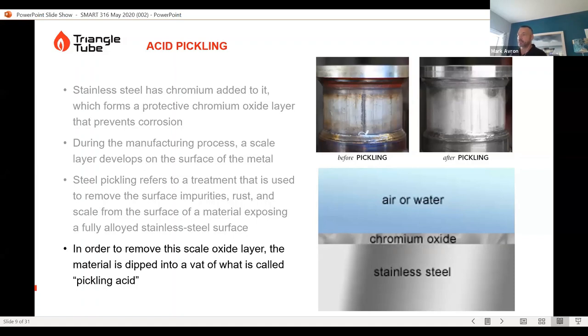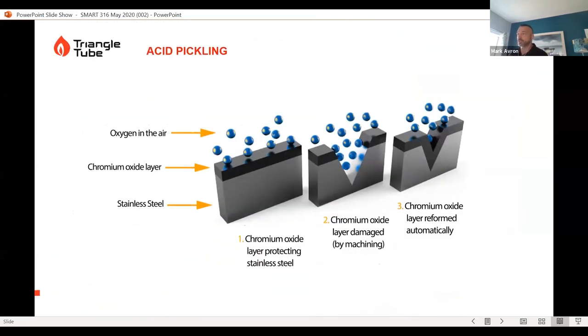In order to remove the scale oxide layer, the material is dipped into a vat of what is called pickling acid, using different acids. The difference between passivation and pickling is that passivation uses milder acids to clean the surfaces, and they don't result in as deep a layer of the chromium oxide. So pickling adds to overall corrosion resistance.